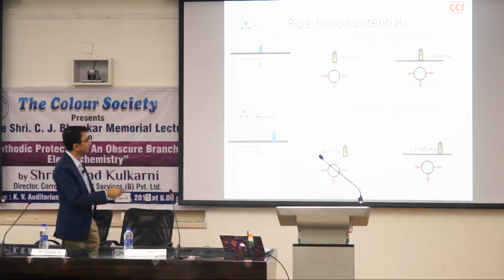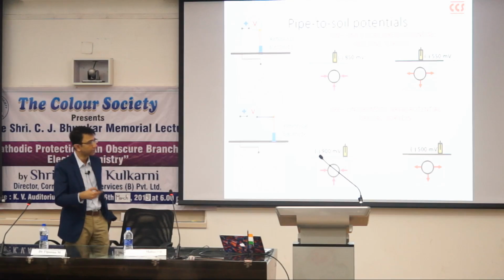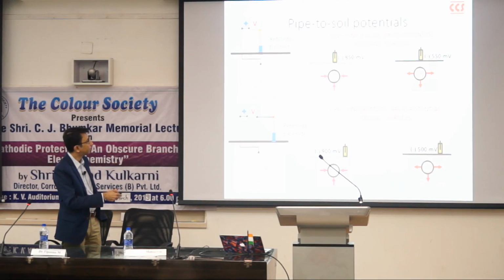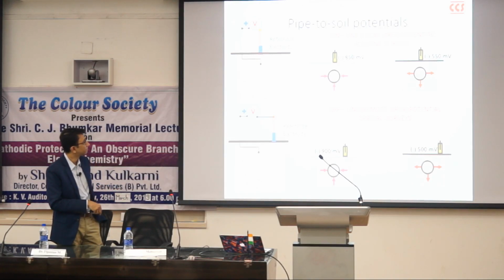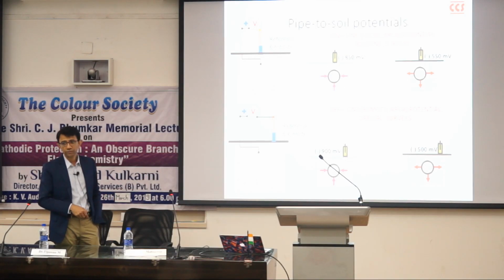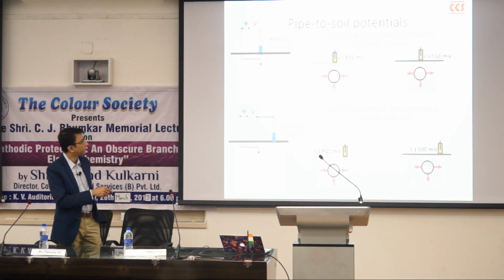And as you can see here, this depicts the pipe which is receiving current, so it is cathodically protected. And we find that we get a measure of minus 850 millivolts with respect to this reference electrode. You can see this picture here where the pipe is not receiving current, it's actually discharging current, it's corroding. So if the pipe is corroding, the potential that it exhibits is obviously not as electronegative as when it is receiving current.